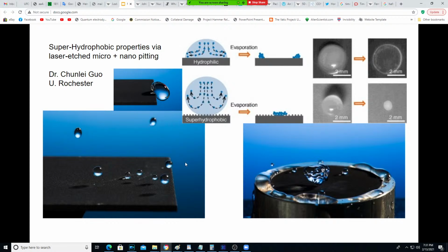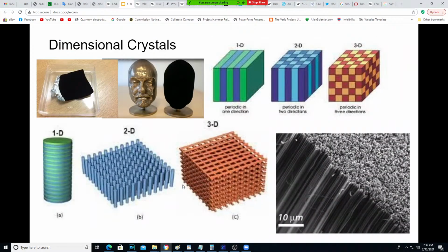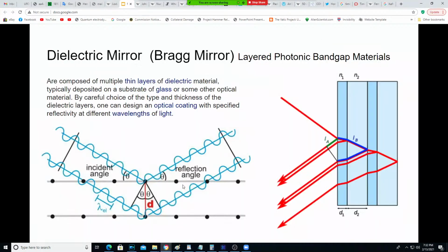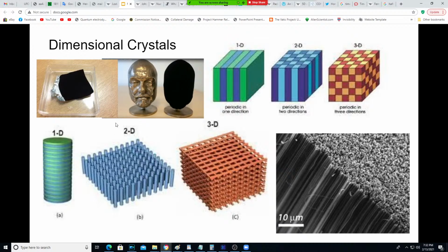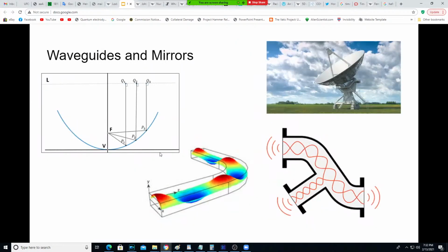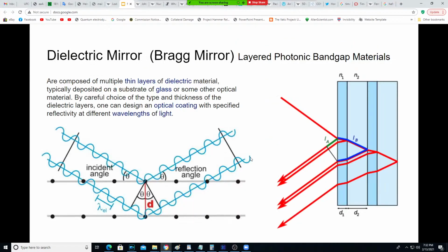And then the application for if you take epoxy thin films and then etch each thin film and then apply them in layers that are tuned to different layers, you can make dielectric mirrors, which we'll get into in just a second right down here. But I'll just get right into the dielectric mirrors and then we'll go back. So we have something called Bragg diffraction when incident light hits a crystal or a structure.